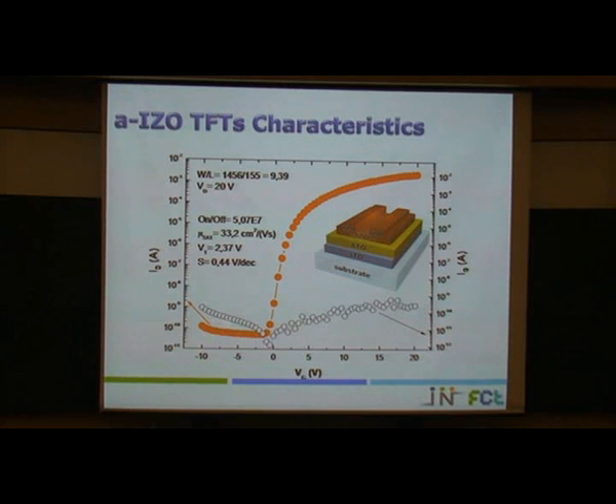And this is a typical transfer characteristic. This is the off state and the on state. The currents we got are very high. So the first time we sent these papers to the referees, they asked us if we had made a mistake, because it cannot be milliamps, usually it is microamps. But no, it's that. We achieved very high values of current for the on state, of the order of milliamps. And even this is not the best device.